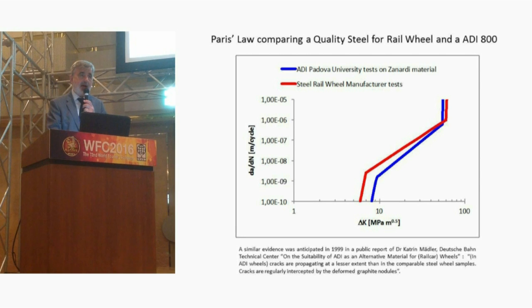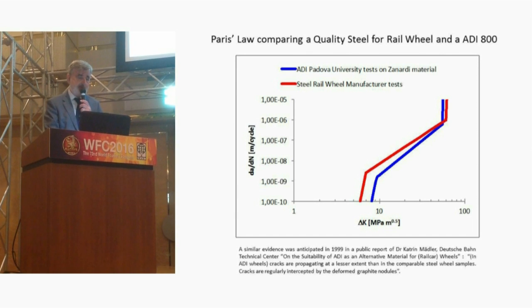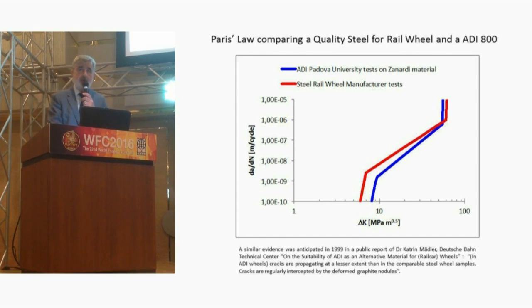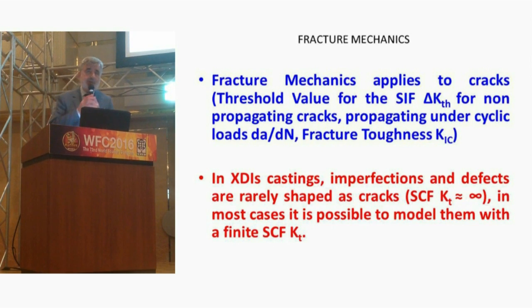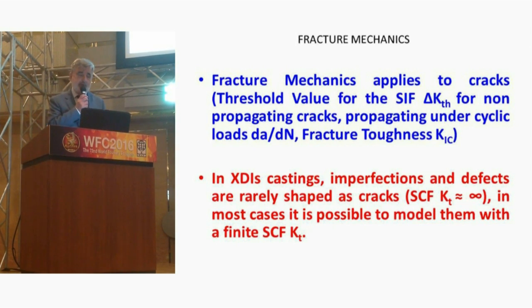And you see how ADI competes very well in the crack propagation rate because of spheroids. This was also recognized by Deutsche Bahn in 1999. So it is important to consider that fracture mechanics applies to cracks. And we have the values of the threshold value for the stress intensity factor, the delta KTH of the previous presentation, for the non-propagating cracks propagating under cyclic loads, and the fracture toughness K1C.